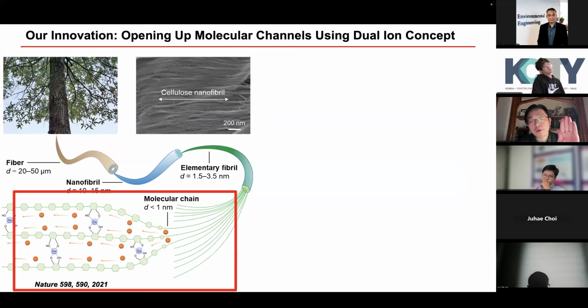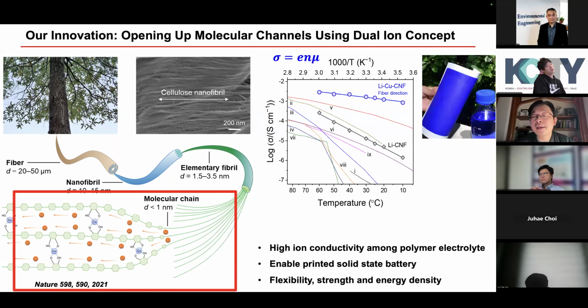We take the wood fiber, which is made of small molecular chains, and we basically open them up by soaking the fiber in the copper solution. Once you open it up, you can put the lithium ion inside the molecular chains. So you have a lot of ions. That is the high N number.